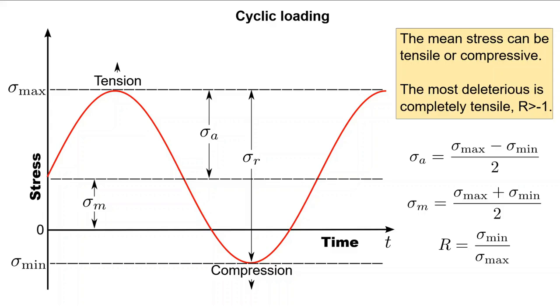The fatigue regime, that is, the loading conditions that are operating, can be categorized by the load ratio, R, which is the ratio of the minimum stress versus the maximum. While fully reversed loading, that is, the magnitude of maximum tensile stress is equal to the compressive stress, is indicative of a Wohler-type scenario, it is the least aggressive fatigue condition. In fact, the more tensile a fatigue cycle is, then there will be fewer cycles that can be withstood before failure.